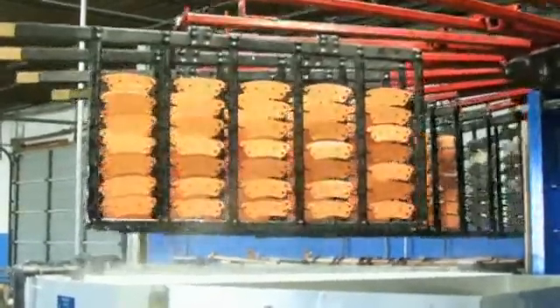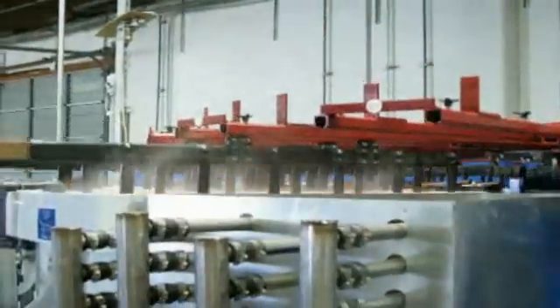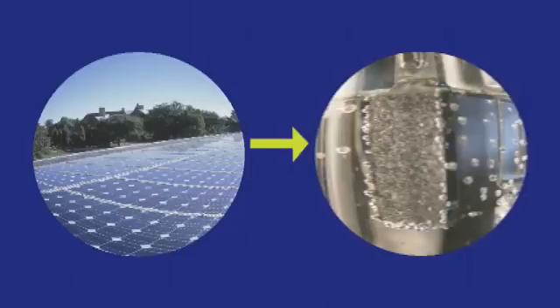Given techniques similar to those used in the electroplating industry, Nocera believes the new catalyst may be easy to scale up. Kanan just puts cobalt ions and phosphate in solution, turns the potential to 1.5 or 1.6 volts, it electro-deposits, and then starts making oxygen — a really easy thing to manufacture. Nocera looks forward to the day when mass-produced devices built around the cobalt catalyst are powered by photovoltaic solar cells, yielding a totally renewable energy system with no greenhouse emissions: H2O plus light gives hydrogen plus oxygen; hydrogen plus oxygen gives energy and water back again. Such a system would convert sunlight into useful chemical energy, just like plants do.